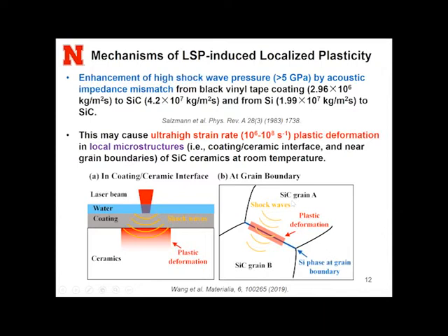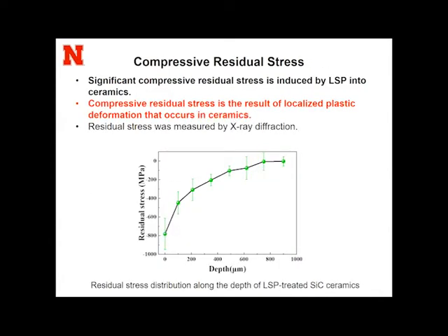So in general, we think that this high shock wave pressure, together with the ultra high strain rate, because the laser pulse duration is very short, just a nanosecond, combined can generate some localized plastic deformation in ceramic. I would say this is still a preliminary theory, and I hope some modeling can help us to explain the mechanism. But no matter the mechanism, the result is clear.